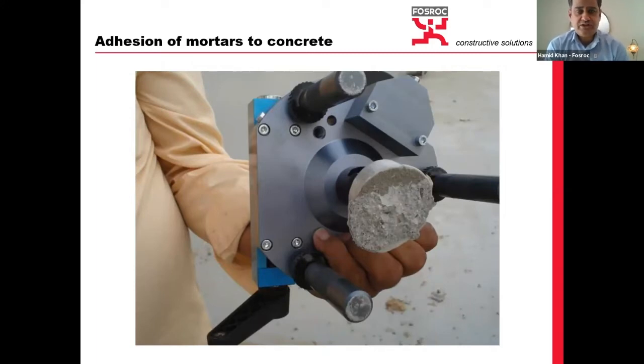The next thing is the bond strength, which is for the integrity of the repair mortar. So the repair mortar should have an excellent bond strength with the concrete. Now, just to make a point here, the bond strength that is normally mentioned as per the standards, tested in the lab and mentioned in the technical data sheets, you can't achieve that at site most of the time. So there are specifications that outline the bond strength or pull-off adhesion test requirements at sites. There are acceptable limits for that. It could be 0.7 or 0.8 megapascal. Normally micro concrete, which is form and pour, and the sprayed mortars can go even 1 megapascal plus, and even much higher than that, but this is a rule of thumb.